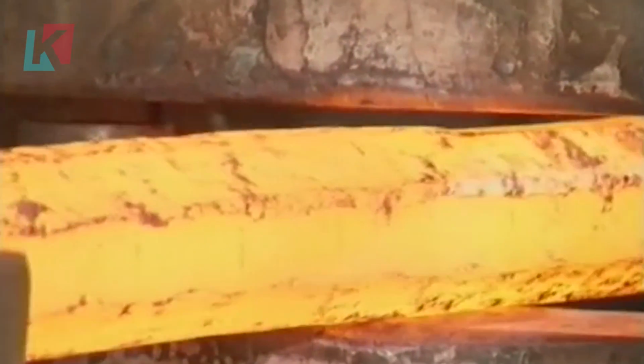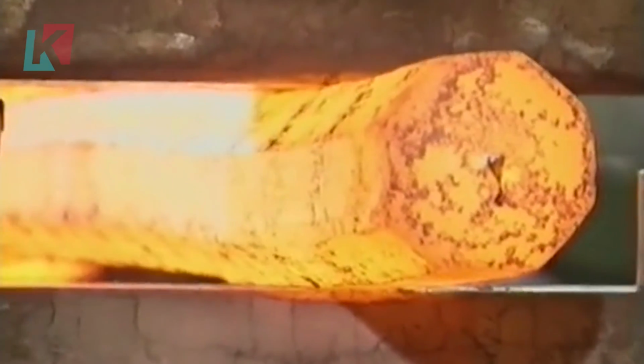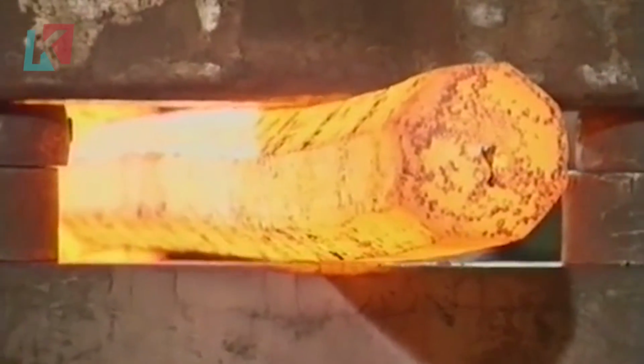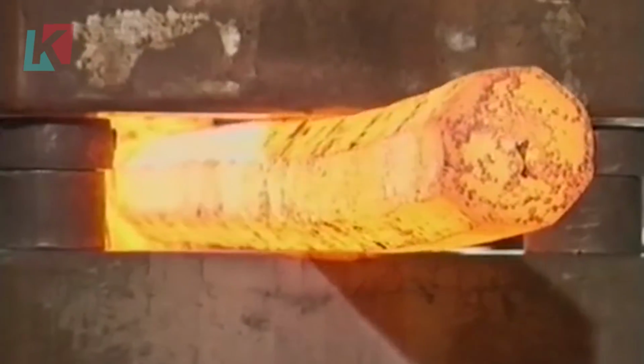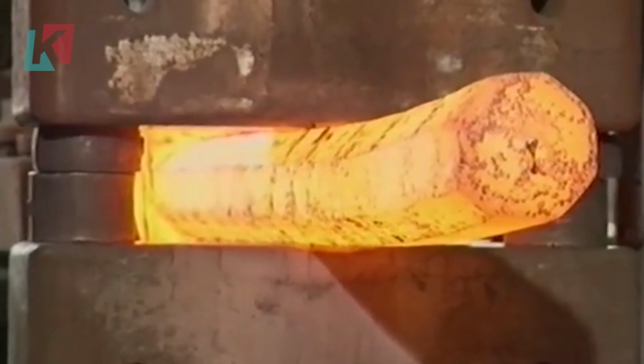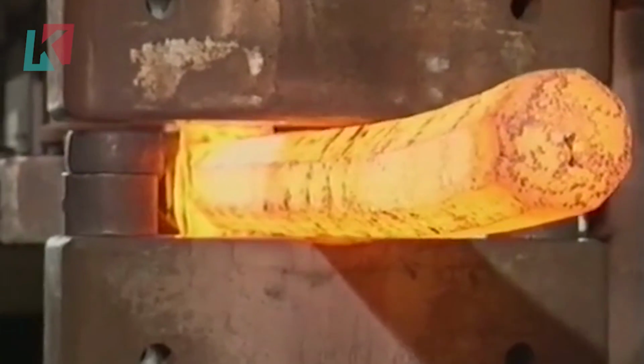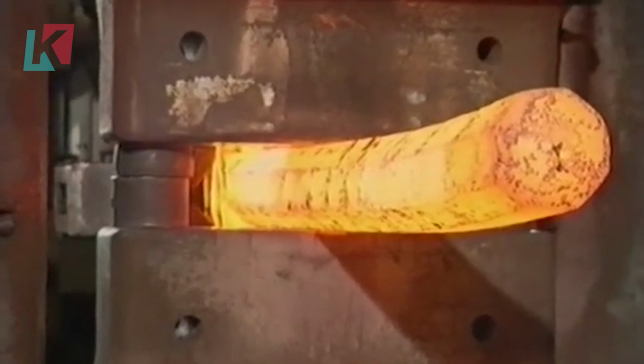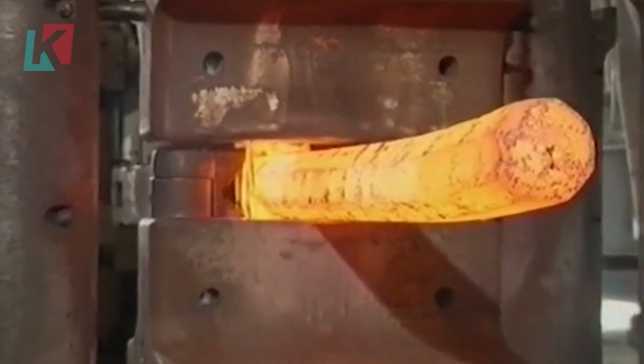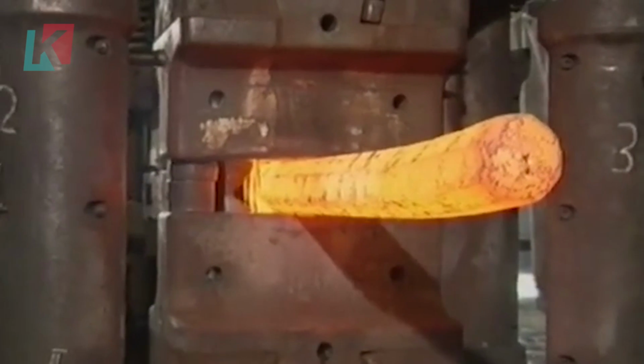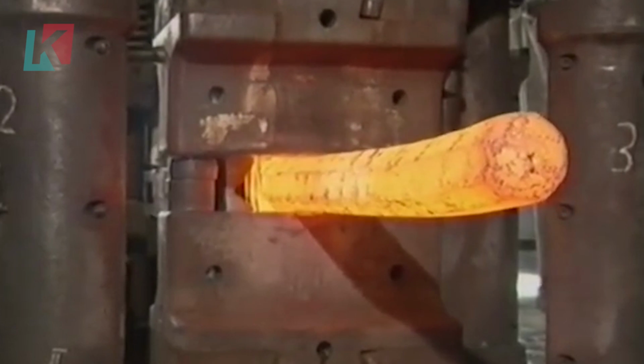The grain refinement achieved through open die forging is remarkable. The original cast structure with grain sizes of 5 to 8 millimeters is reduced to 0.5 to 1 millimeter, creating a fine, uniform microstructure that provides superior mechanical properties: higher strength, better toughness, and improved fatigue resistance.